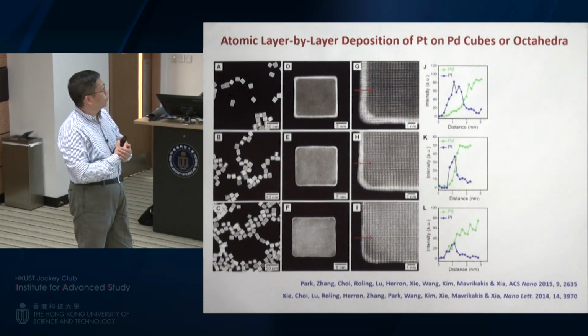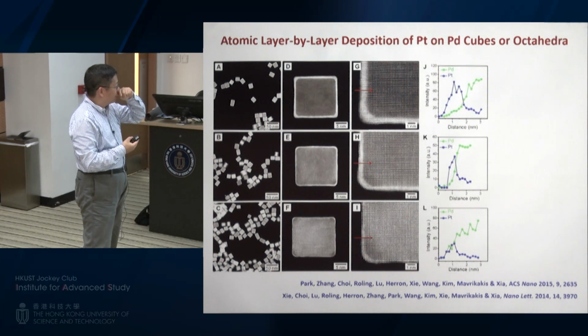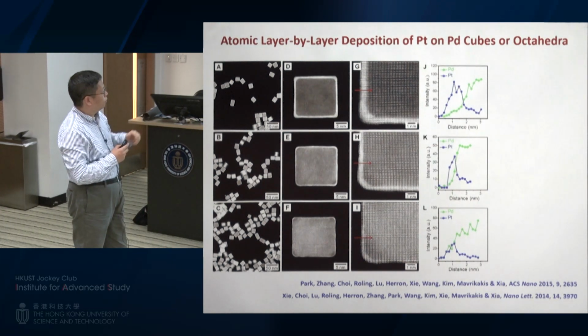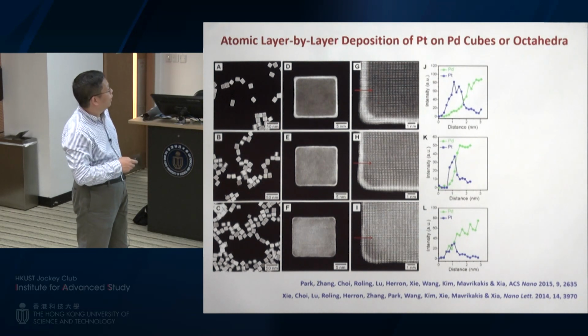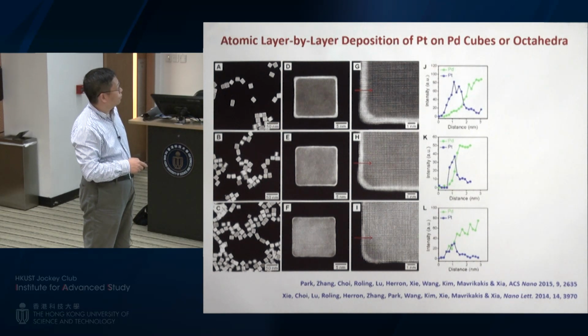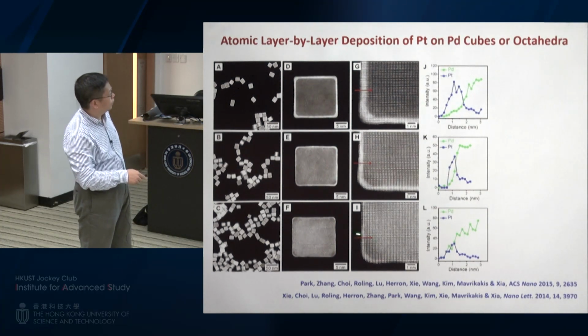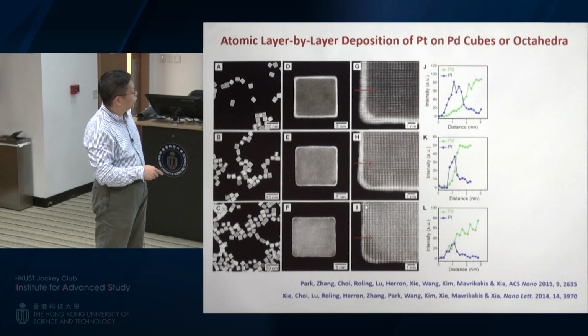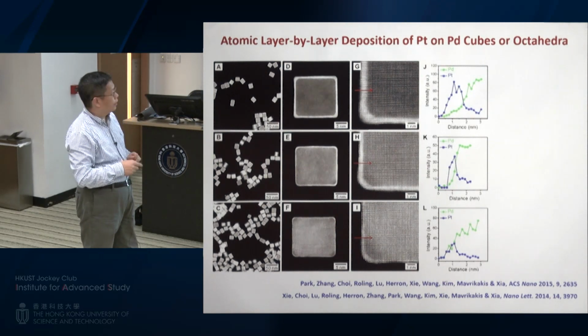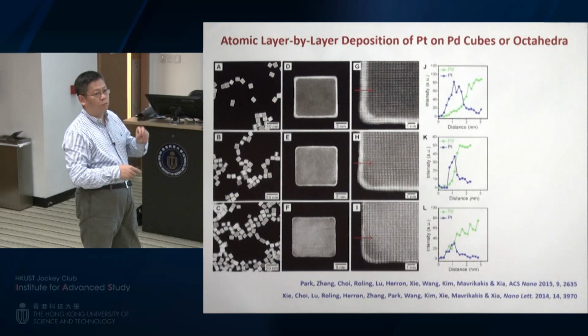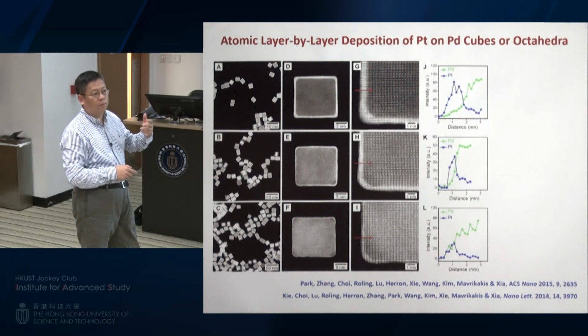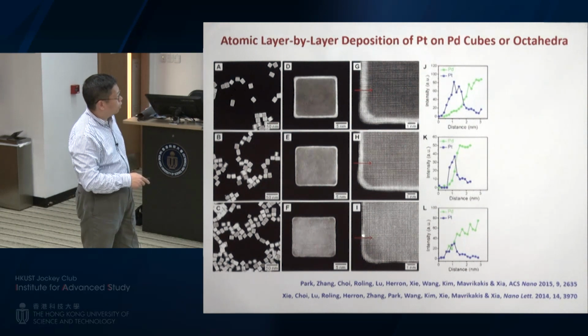And core shell is also important, okay, and let me show you some examples. Actually, they can become the focus for the last few slides in this talk. The idea here is to deposit platinum on palladium nanocrystal seeds, so you can make a core shell structure. This is at different levels of magnification. And you can see the platinum can be uniformly coated as a conformal shell around the palladium. You can control the thickness by controlling the ratio of platinum precursor relative to the palladium nanocrystals. And you can have 2 atomic layers deposited, 4 atomic layers, 6 atomic layers, and so on and so forth.